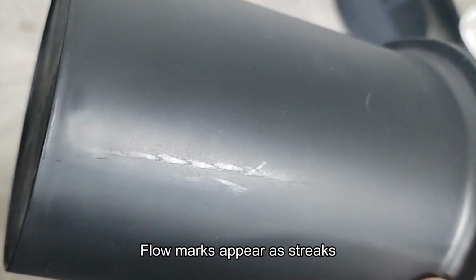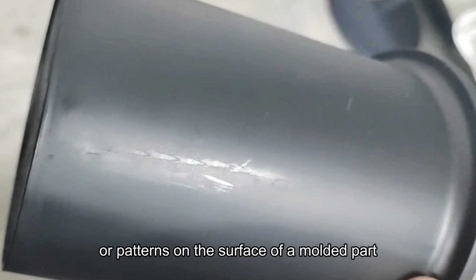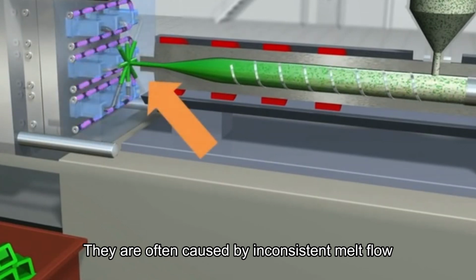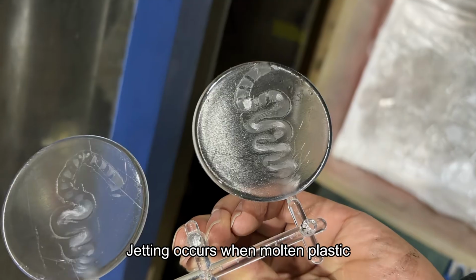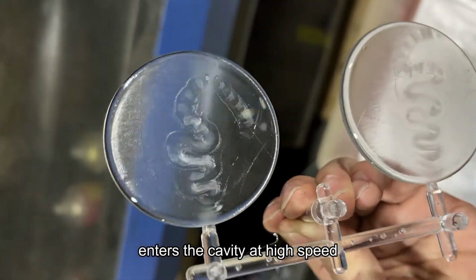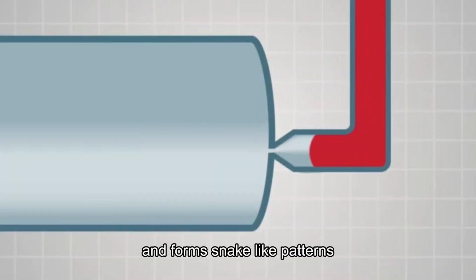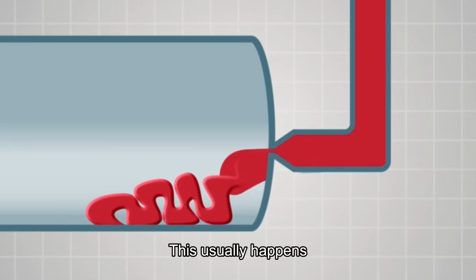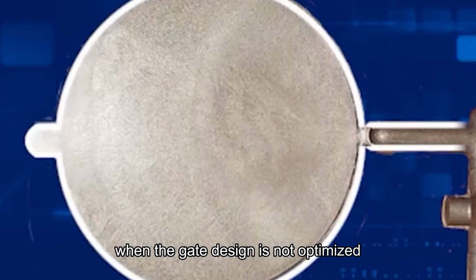Flow marks appear as streaks or patterns on the surface of a molded part. They are often caused by inconsistent melt flow or rapid cooling during filling. Jetting occurs when molten plastic enters the cavity at high speed and forms snake-like patterns instead of flowing smoothly. This usually happens when the gate design is not optimized.